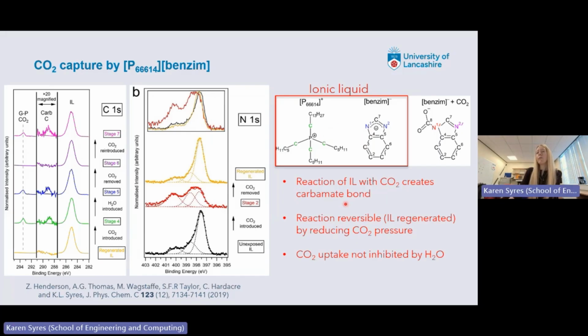What we find when we look at this, so these are our XPS scans. Basically, we have to find out the binding energy of the electrons. So this is a scale showing our binding energy, and we're looking particularly at the nitrogen atoms in the benzim and then the nitrogen atom when it's bonded to the CO2. I won't go through what each of these peaks mean, but you can see here at the bottom, the black peak, this is before we've exposed our liquid to CO2.